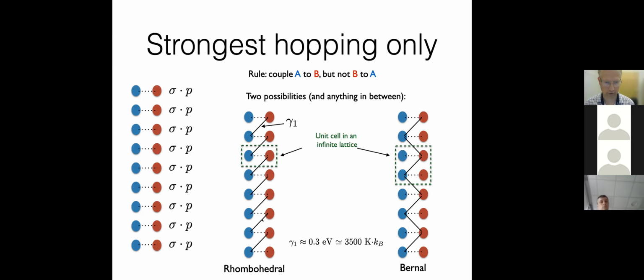and if you make this, where the different atom always couples with strong coupling, you have rhombohedral stacking. If you have this zigzag pattern here, you have Bernal stacking. And the size of the coupling is called gamma 1. It has a typical size around 0.3 electron volts in graphite, which corresponds to around 3,500 Kelvin in temperature units.